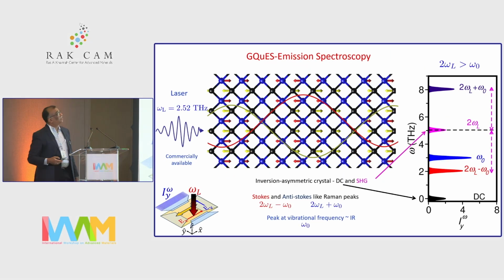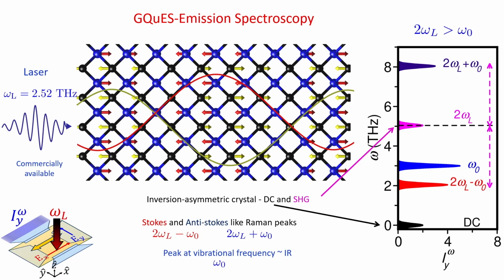The second is emission spectroscopy, where you can also imagine light shining on the channel, and then you measure emitted light with a perpendicularly polarized electric field, and the spectrum of that emitted light will also have a structure as shown here. For inversion asymmetric, non-centrosymmetric structure, you will have rectification and 2 times the light frequency, but also due to the vibrational modulation, you will have additional peaks here which allow you to measure vibrational frequency of the system. So these are 2 scenarios in which the GQuES spectroscopy can be implemented. One is transport and one is emission.